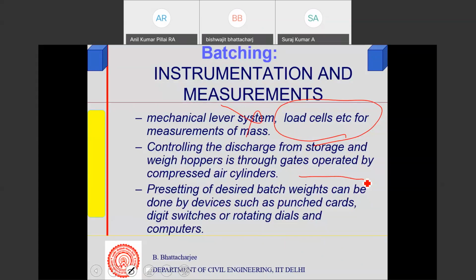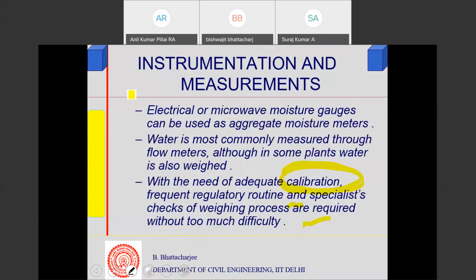You know, if for example, water is W and cement is C, W by C is what you propose to give. But if you have made an error, it will be W plus minus delta W divided by C plus minus delta C, which means that the strength will vary more if it is W plus delta W divided by C minus delta C. The extreme case, you have very high water. If your weighing is not proper, it goes beyond tolerances. There are a certain amount of tolerances the codes allow you, even if you have calibrated properly.